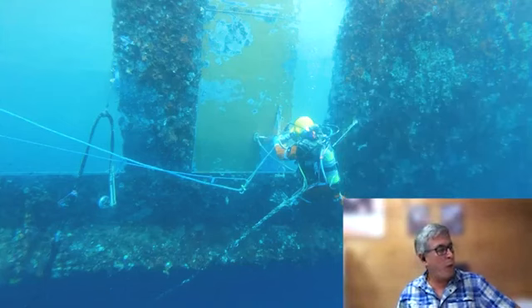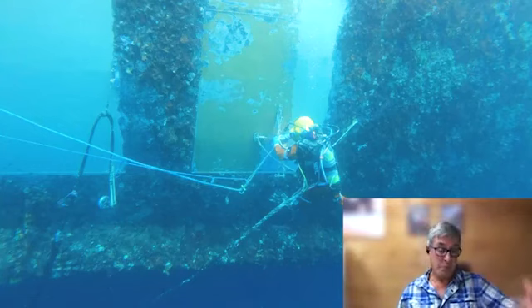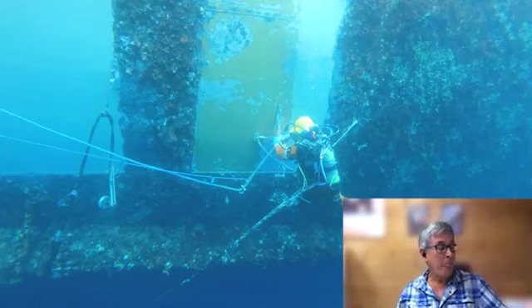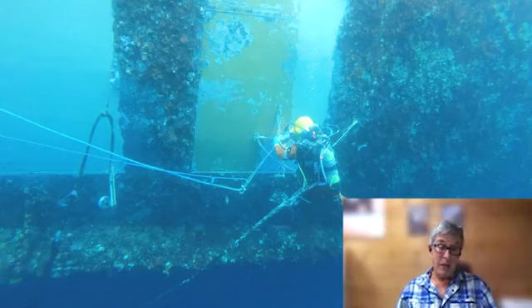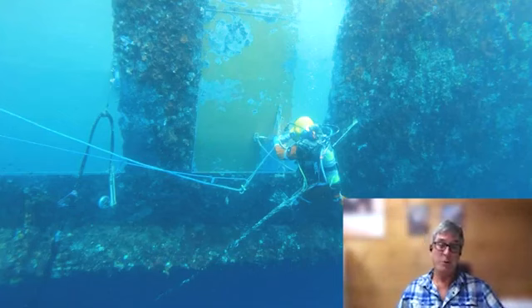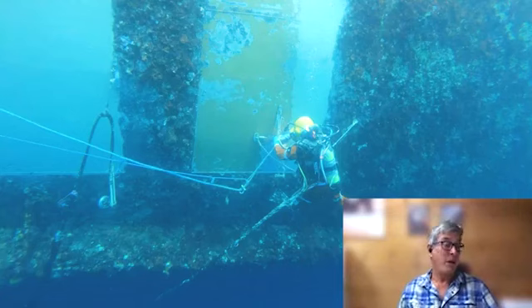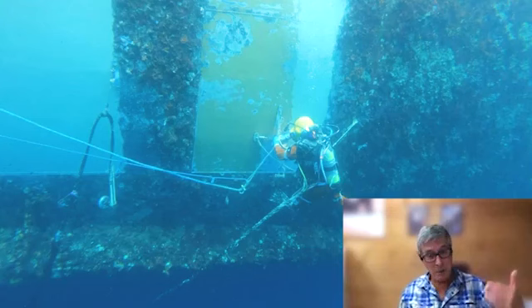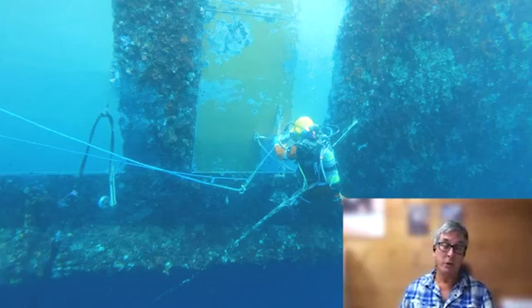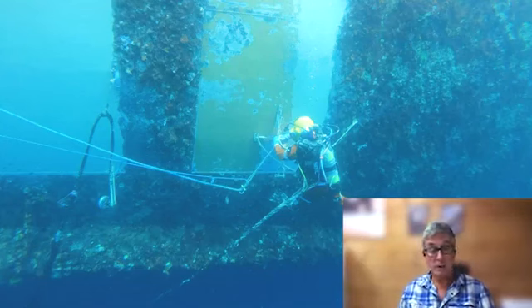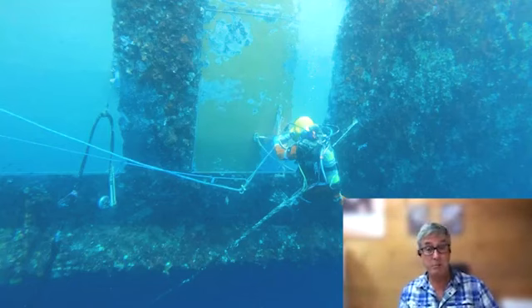Well, while we're painting small areas like this, where we're detailing corroded areas, we use a pot of product. We mix up about a litre of product, and it goes down to the diver in a small, if everybody knows, B&Q paint pot, where the applicator dips in. If we're doing larger areas where we can continually paint, we pump paint down to the diver using a pluricat, which ensures that he gets fresh product out of the end of his applicator constantly.